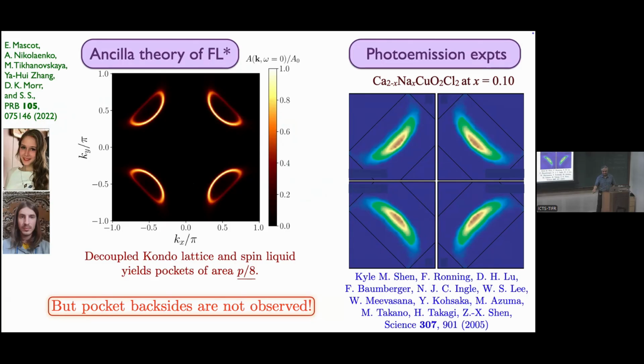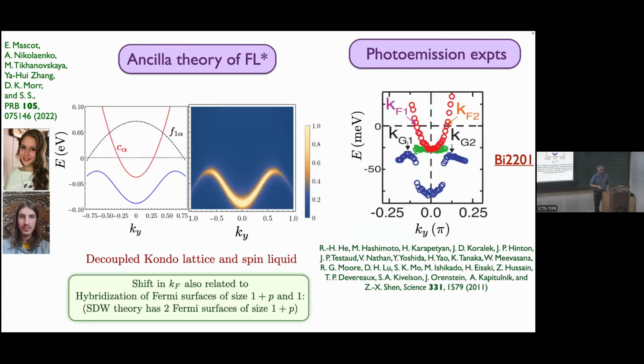But of course, the Yamaji effect has given us renewed enthusiasm for this model, even though this doesn't work at the moment. You can also look near the antinode where I showed you this dispersion, and you get exactly the same dispersion that comes out with no further fitting parameters.